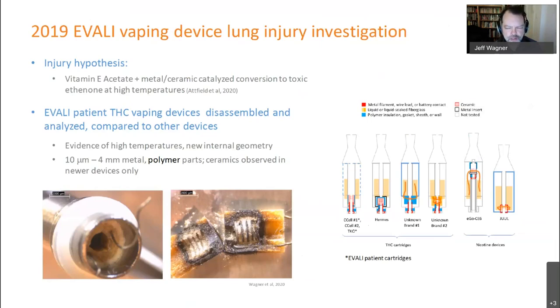So we started taking apart patient vaping devices, comparing them to other devices to see if we could find these internal parts. And we did. We found, as you see on the lower left, some evidence of charring and high temperatures inside these devices, as well as a different internal geometry than previous vaping devices. We also found metals and ceramics inside. So all that is consistent with the hypothesized injury mechanism. What we also found was polymer parts inside in a great many of the devices, new and old, which I didn't expect to see.